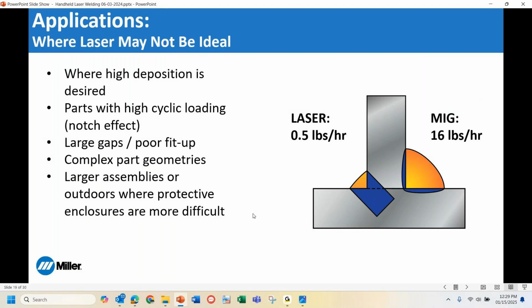So we definitely want to consider what is the result that we're trying to get by looking at a new technology. If we're doing a weldment where there's high cyclic loading or notch effect, where there's maybe larger gaps, and we need to fill that gap in, that's going to be something where traditional welding processes like MIG or TIG might still be ideal or more suitable. And laser welding, even though you could do multiple passes, we're still only depositing a much smaller amount of filler metal than with those other welding processes.